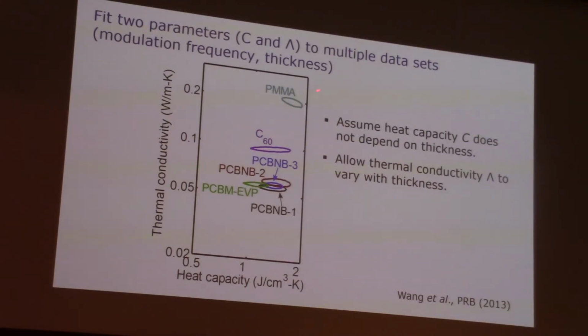This is PMMA, a typical polymer. This is C60, the fullerene film assembled from the fullerene. This is a whole variety of different types of fullerene derivatives deposited in different ways, and actually this is just a couple of them, but we did 10 or something. And they're all very similar, they're all about this 0.05. So the bottom line is the heat capacity doesn't change very much, but the thermal conductivity goes down.